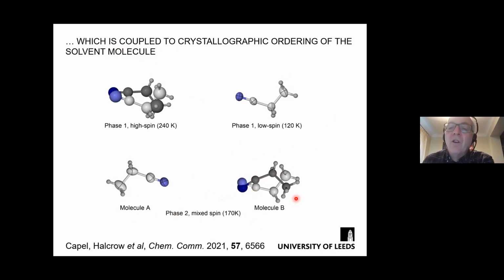It's the ordering of the solvent, and the propionitrile solvent has this bent shape. It's very much bent here like a boomerang. So it can be oriented up or down, and that gives rise to the disorder. Acetonitrile, MeCN, just looks like this. It's linear. You can't have the same up-down disorder for a linear solvent molecule. So we don't have the intermediate crystal phase during the spin crossover. And I think this is the difference.